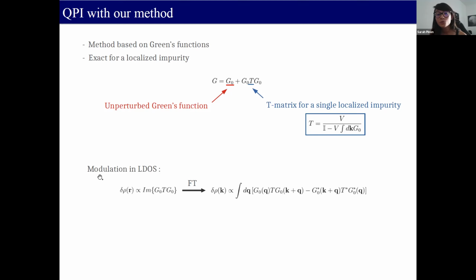So what we want to compute is the modulation in the local density of states. We call this delta rho, and in real space it is proportional to the imaginary part of G0 T G0, which is the perturbed part of the Green's function. If we do a Fourier transform of that, we can obtain delta rho in K space, and we have a formula that looks like this.